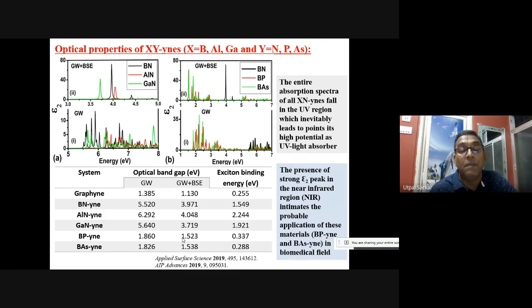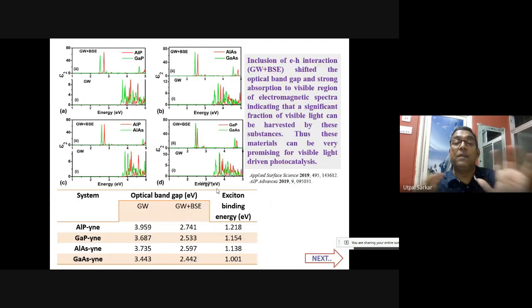So these are the optical band gap with GW, GW plus BSE, and this is the exciton binding energy that we have calculated from here. Okay, so that is something you can also get. It is a very high level calculation, time consuming and computationally expensive, but finally you will get results which you can compare with your experiment. Okay, so this is a very interesting one.